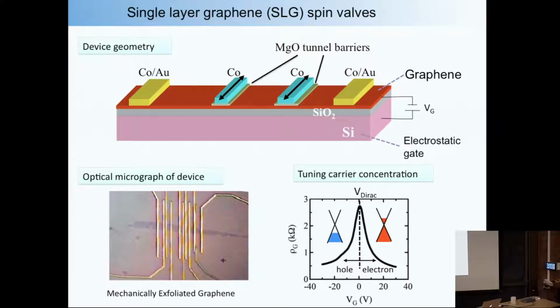And then there's two outer electrodes, which are typically non-magnetic, but in our early studies we also used cobalt, so that's a trick. And then there's an insulating layer, and the silicon substrate is conducting, and you apply a voltage to the substrate, and this acts as an electrostatic gate. And let me just show you a picture of the device.